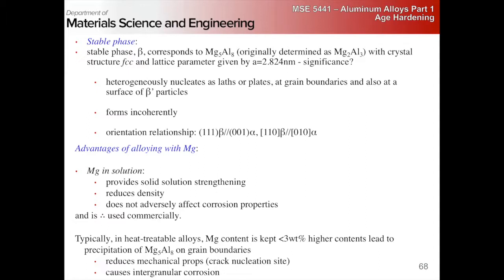Yeah, so it nucleates heterogeneously at grain boundaries at relatively low temperatures, and it tends to form nearly continuous phases on the grain boundary, really susceptible to stress corrosion and cracking, right? So the Navy is actually having a huge problem with this right now.